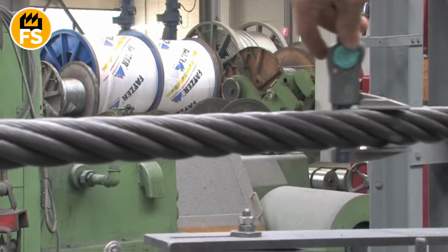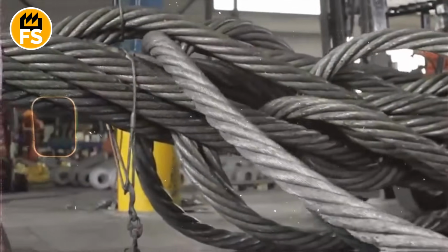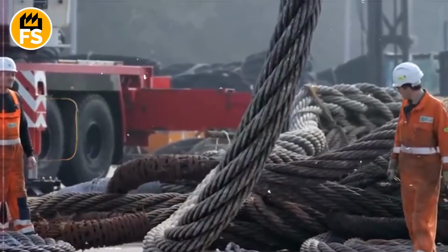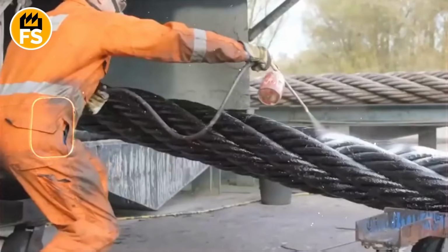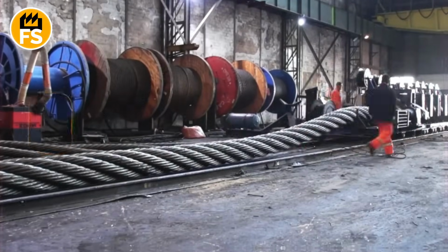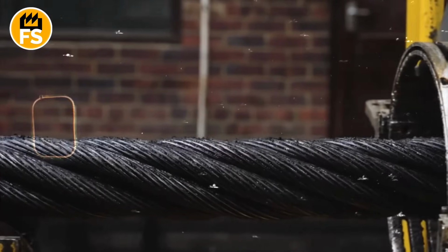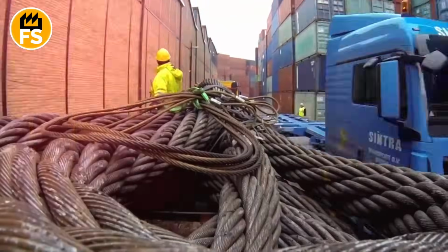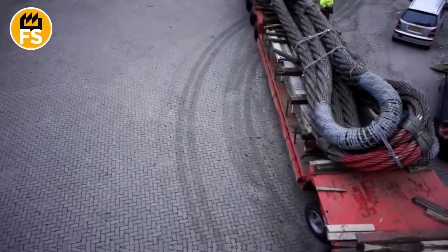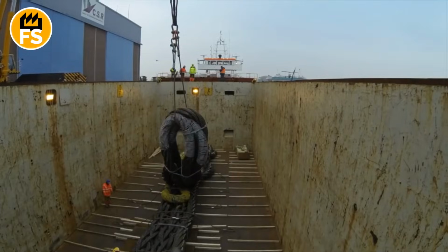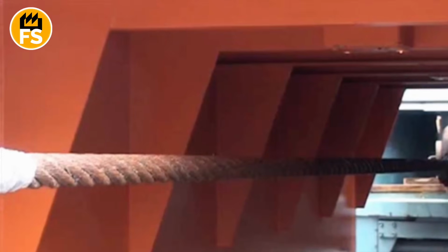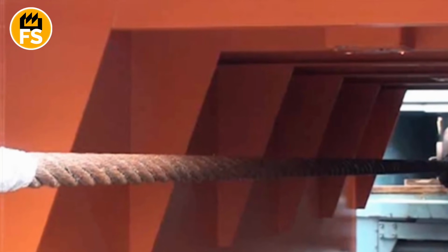spans. When you're dealing with slings 280 feet long and more, they pay special attention to uniformity along the entire length. The rope is manufactured without joints, in a continuous process, to avoid weak points. It's wound into massive coils that can weigh tens of thousands of pounds. Already at this stage, they conduct initial tests, measuring actual breaking strength and comparing it to calculated values.